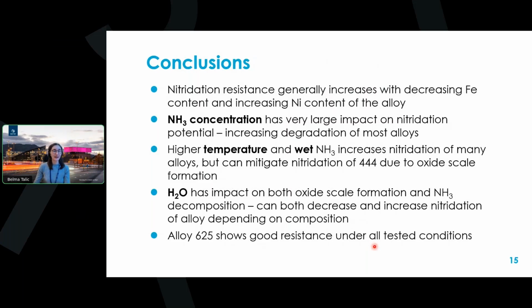So I finally reached the conclusion. In summary, what we saw from this study, studying 7 different alloys and 7 different exposure conditions, is that generally the nitridation resistance increases with decreasing iron content and increasing nickel content of the alloy. We saw that the ammonia concentration had a very large impact on the nitridation potential, and it led to increased degradation of most of the alloys.